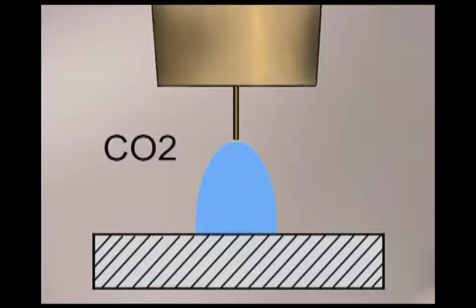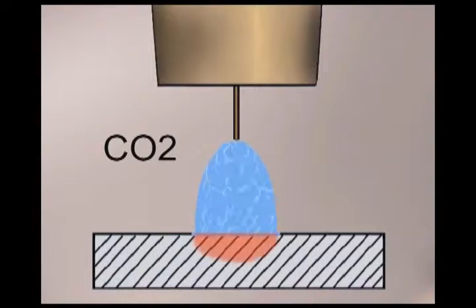Straight carbon dioxide does not transfer current well and requires a higher voltage. A wide arc stream is formed with a lot of energy that breaks up surface oxide and allows good penetration and weld fusion. While all that arc energy does help to produce a strong weld, the problem with straight carbon dioxide is that it just isn't any fun to weld with. The high voltage and arc energy causes a harsh arc that creates more weld spatter and agitates the weld puddle, making it difficult to control.